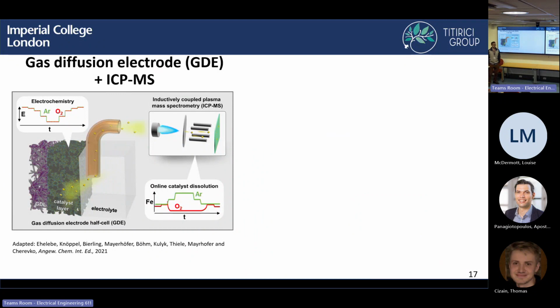It's kind of known in the literature for these catalysts. For any electrocatalyst, normally you do some preconditioning step, but people never know, especially for these iron nitrogen carbon, if your preconditioning is killing the catalyst, activating the catalyst, or doing nothing. It depends on the catalyst. But always for electrocatalysts, you do some preconditioning. I guess in the battery, you probably do the same. Also with very porous ones, you can have some bubbles.